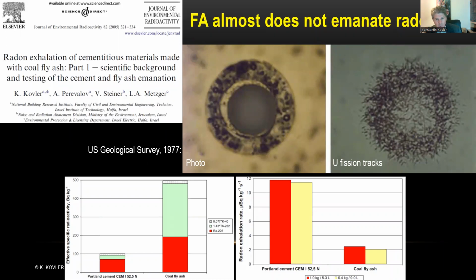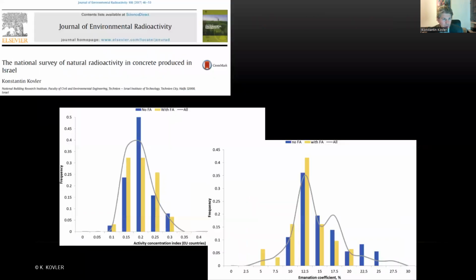All the industry was in deep shock after years and many efforts of educating the industry how to use and how to promote different recycling solutions for coal fly ash. And we studied in depth the effect of natural radiation. We compared different materials, concrete containing and not containing fly ash. We came to the conclusion that the total radiation dose from both gamma and radon is almost the same, because radon emanation is much lower.